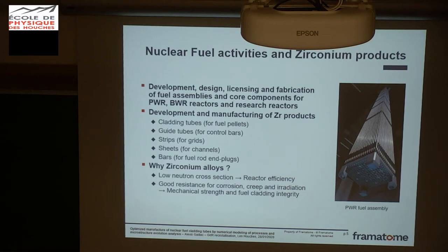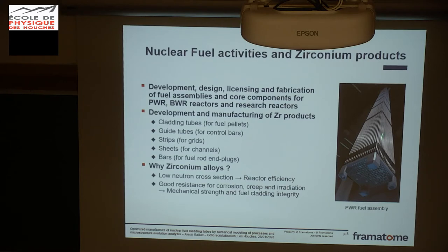Why do we use these zirconium alloys? We use them in the nuclear industry thanks to their low neutron cross-section, because it's needed to have good reactor efficiency — the neutrons have to travel from one uranium atom to another for an efficient reaction. Zirconium alloys also have good resistance to corrosion, creep, and irradiation throughout the life of the fuel.